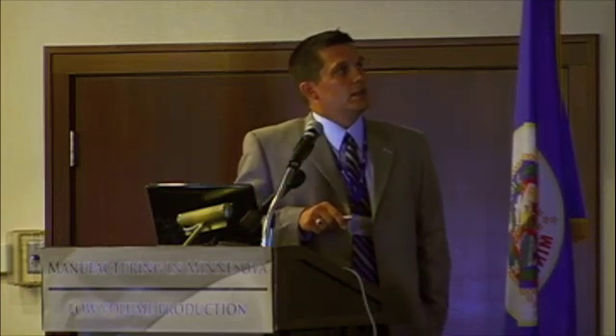So Honda did this case study. This is an aluminum tool. This is a P20 tool. They shot the same part, shot count 61,000 parts, polypropylene. So it wasn't the hardest material to ever shoot. Cycle time, 50 seconds for the P20, 30 seconds on aluminum. So you can actually reduce your costs by running those volumes out of aluminum.